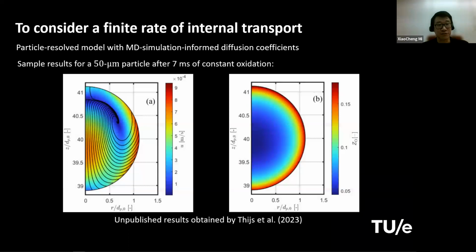Anyway, so there are some preliminary results to look into this direction. But as I said, if we want to resolve what happens internally inside the particle, you need a particle resolved model, and also you need some diffusion coefficients. But our student managed to get this diffusion coefficients of Fe and O within this high temperature liquid mixture using MD simulations, and this allows him to proceed with some particle resolved model. And this is just some very preliminary result that he obtained.